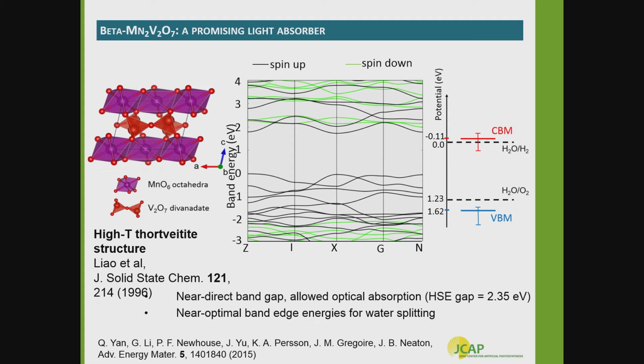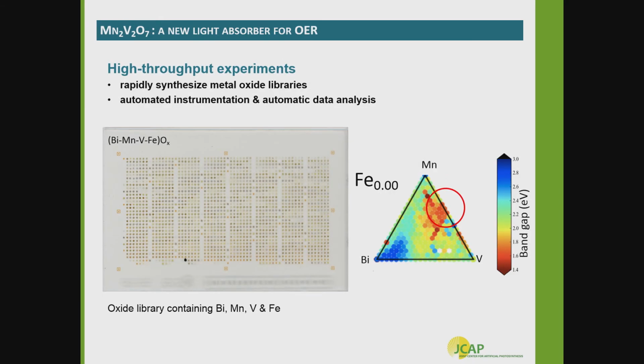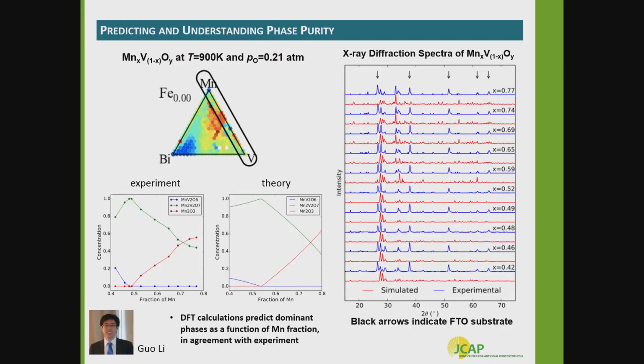manganese vanadate phase, this high temperature structure of manganese vanadate, exhibited an attractive band gap and nearly optimal band edges for water splitting. So the experimental team zeroed in on manganese vanadate phases and identified a number of candidate compounds, and in fact there was very, very good experimental and theory comparison between the stable phases at a given composition in both theory and experiment.